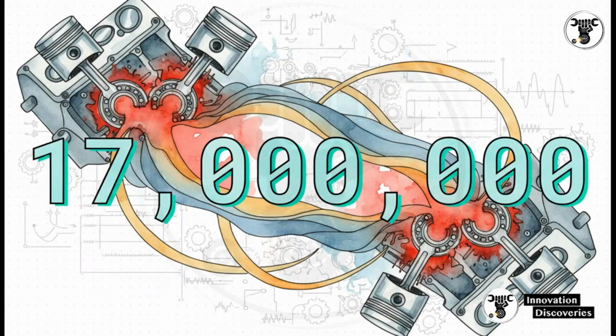Which brings us to this absolutely massive number, 17 million. This is the peak instantaneous PV rating. That's the unit load multiplied by surface velocity inside a high horsepower V8 screaming at 6,500 RPM. Now, typical lead tin overlays max out around 50,000. So how on earth does it survive a 17 million PV spike? Well, it's because that immense load pulse only lasts for mere microseconds.